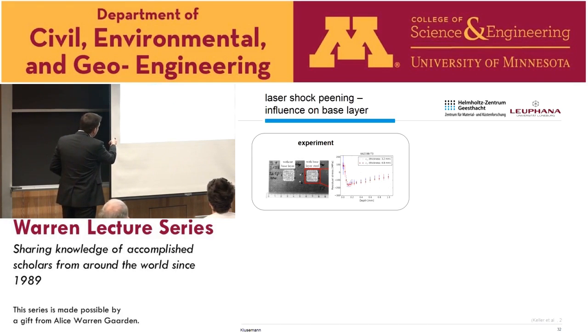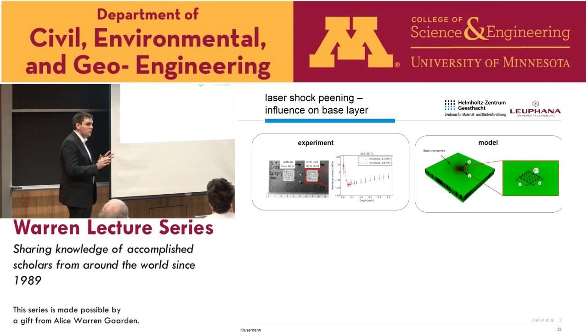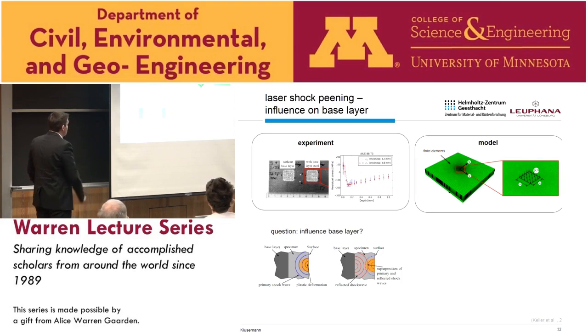So we studied then the influence of the base layer. We did the experiments. We obtained here, of course, our residual stress over the depths. And you see you have an increase in depths, and then it goes, of course, back to 0 at some point. Laser shock peening is a process which introduces relatively deep compressive stresses.